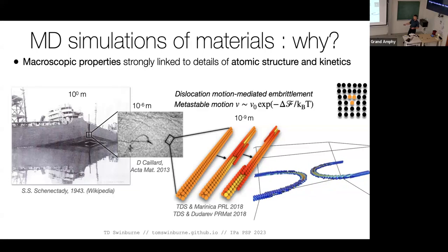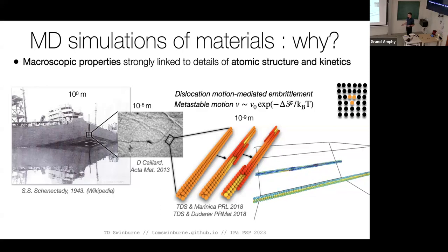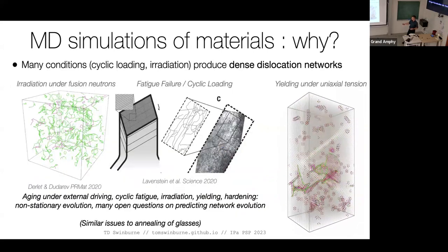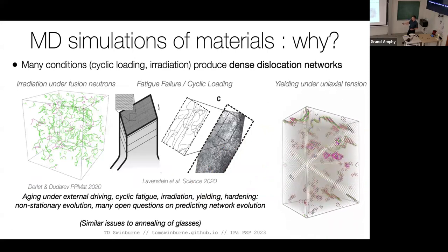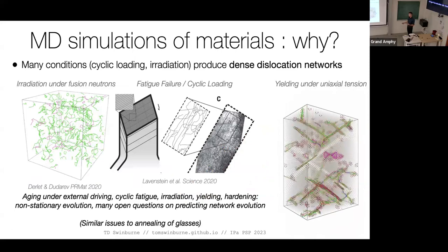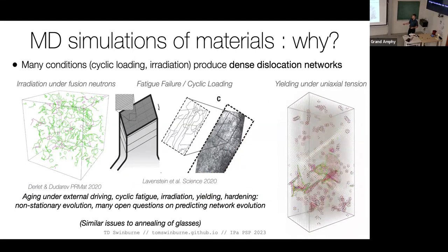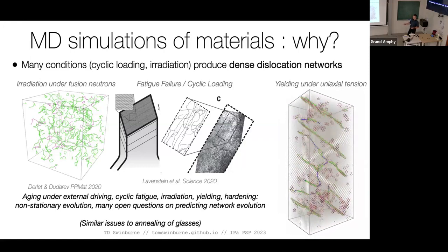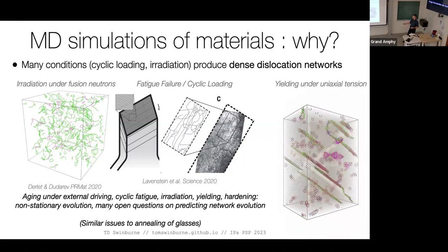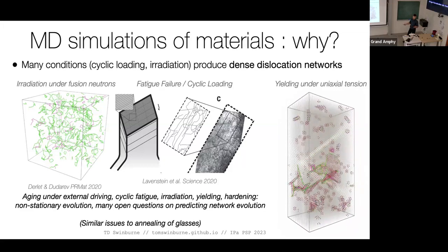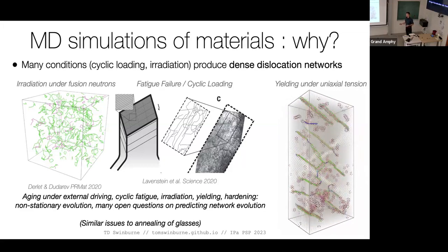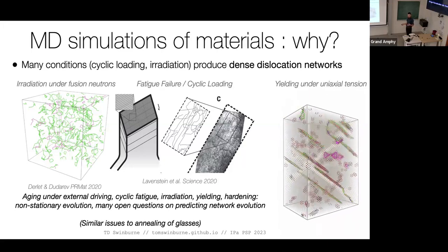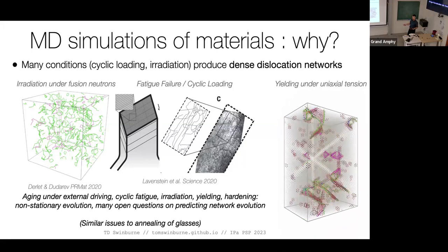At different temperatures, this can really influence the structural properties of metals. There's the case of a ship put in very cold water — the temperature was too low for dislocations to move, stress built up, and it cracked. Away from idealized settings of very clean dislocation lines, in more general settings we have much more complicated flow: highly transient atomic connectivity, many junctions forming and breaking, and quite complicated network dynamics that play a role in long-time aging under high-energy radiation or fatigue from cyclic loading.